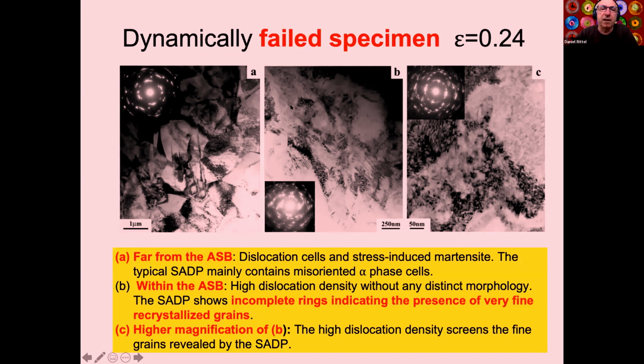Then we go to the failed area where we have a shear band. And if we look inside the shear band, we see a lot of black and white features that we don't really know. Those are dislocations, but what more? But the diffraction patterns are completely different. Look, they are very dense and lots of small dots. That tells you one thing and one unique thing. The microstructure is extremely fine, and you have here nanograins. Okay, we have nanograins. Where do they come from? How did they form? But they are here in the shear band. You have those nanograins.